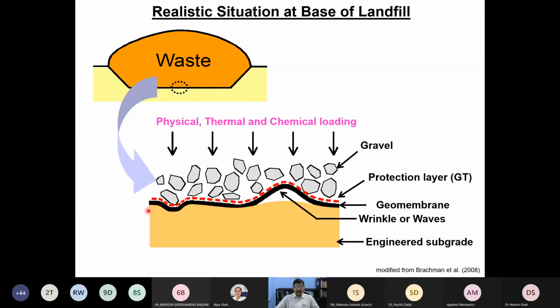So that means your membrane is subjected to aging because of the physical loading caused by the weight of the waste, the thermal loading because of the decomposition of the waste, and the chemical loading because of the leachate composition. So you really need to investigate the combined influence of physical, thermal and chemical loading; the synergetic effect you need to take into account. In addition to that, you do have indentation within the geomembrane because the granular particles are subjected to the overburden weight of the waste, and this will try to poke the geomembrane. And sometimes because of the thermal expansion of the polymer, you do have wrinkles in the geomembrane.